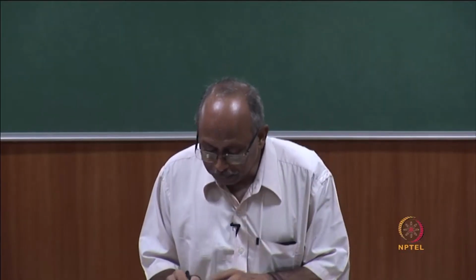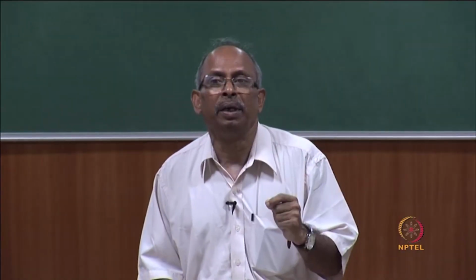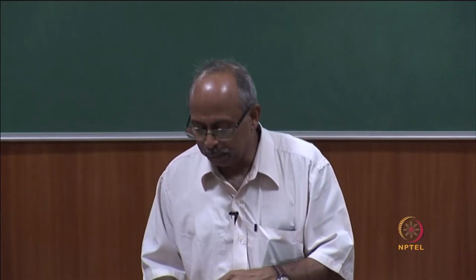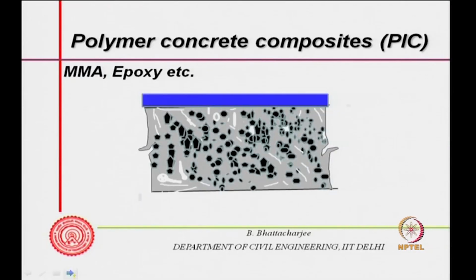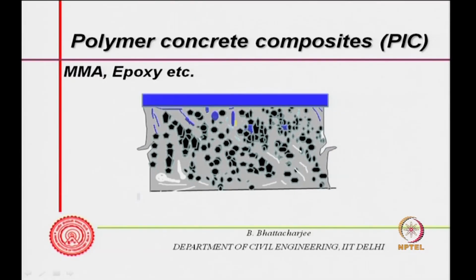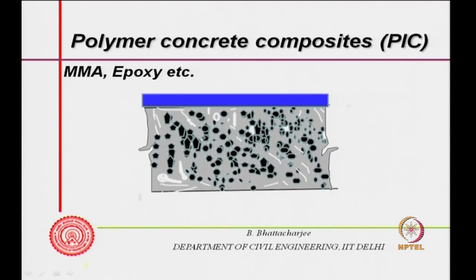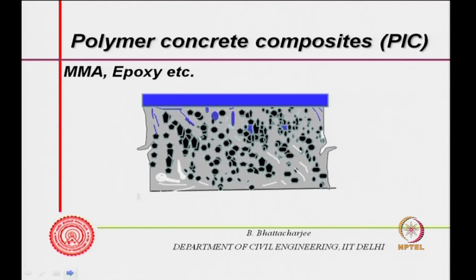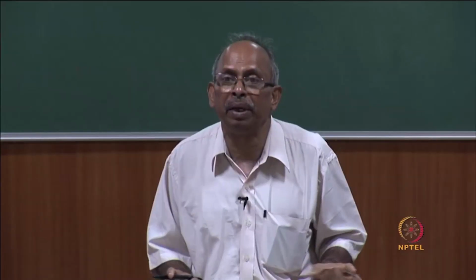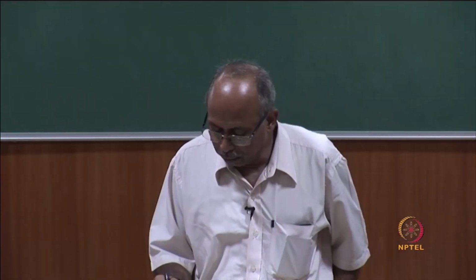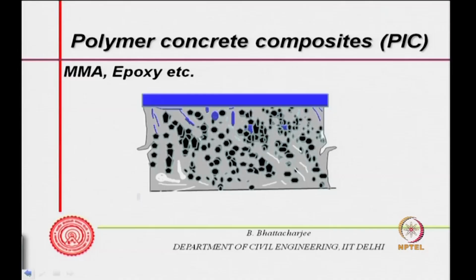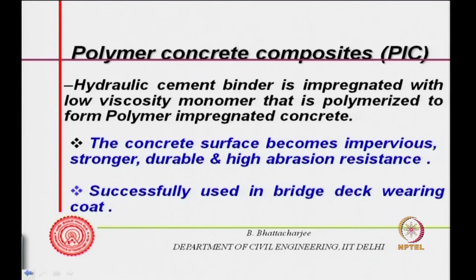So, you actually put in some heating system. Injection is under pressure, while impregnation is just putting it on top, flooding it, and then the impregnation will occur. The polymer will simply get inside and block the pores at the top, and this is polymer impregnated concrete. Polymer impregnation can be done from the top on a flat surface, and obviously the bottom pores still remain, but the top pores are blocked. So, this is the process of polymer impregnation.